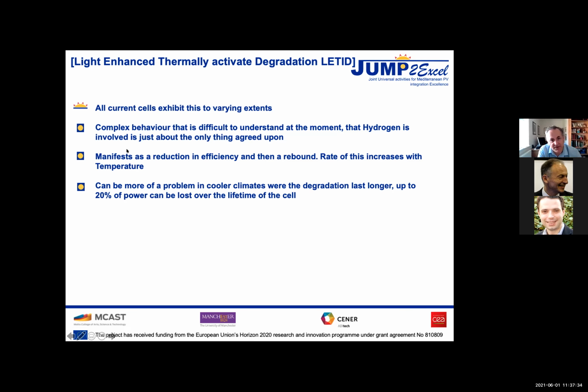But the rate this happens depends on temperature, and so one of the strange aspects of this is that if you put a cell on a roof in Cyprus, where it's really hot, the whole cycle goes through, going down, degrading and rebounding, perhaps in a year, which over a 25-year life cycle of a cell isn't so much of a problem. However, if you put it on a roof in Germany, where it's cooler and the illumination is less, the process depends strongly on illumination as well, then the degradation can take 20 years to occur and recover. So over the lifetime of the cell, we lose a lot of power. That's 20% of the power, so a lot.